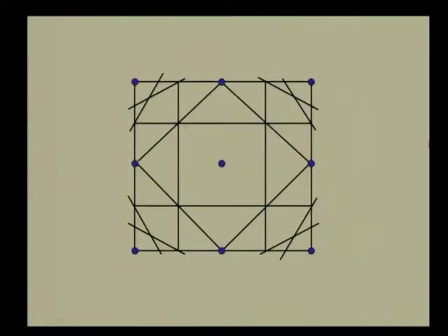So, having got this array of perpendicular bisectors to lines joining the origin to all the neighbors around this central lattice point, we can now identify Brillouin zones based on the definition we have given for Brillouin zones, which is basically that the first Brillouin zone is the region in space around this point which can be reached from this point without crossing a single Bragg plane, and therefore that would be the region that is identified here. Okay, so, this region around this point is therefore the first Brillouin zone.